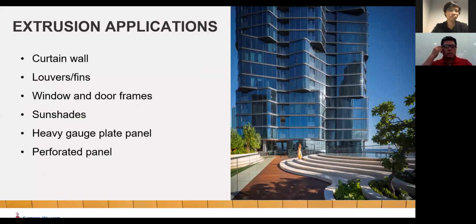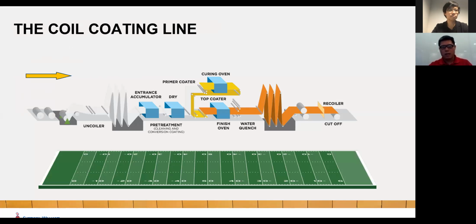Now this is the coil coating line, where you can see the beginning to the end. The whole coil is uncoiled and then goes through the pre-treatment section. Then we have the primer coating section and the top coat coating section. Once it's finished, it goes through the oven, then the water quench, and is recoiled. Okay, so that's the whole process for coil coating.